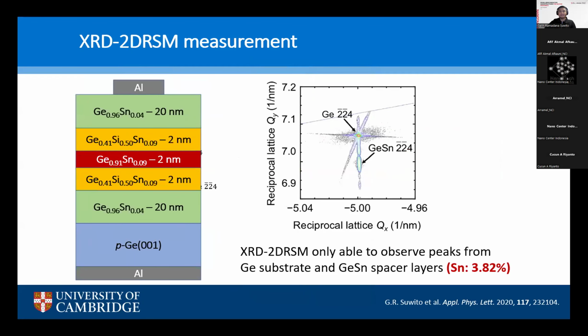Next, the structural analysis was performed by X-ray diffraction with two-dimensional reciprocal space mapping, or 2D RSM. And the mapping result indicates pseudomorphic growth of germanium tin epitaxial layers without the formation of strain-relaxed layers. And by assuming Vegard's law, the tin content in the germanium tin epitaxial layer was estimated to be 3.82% for this sample. However, obviously, the quantum well is too thin because it was just 2 nanometer times 3. So observation through XRD was a bit difficult.